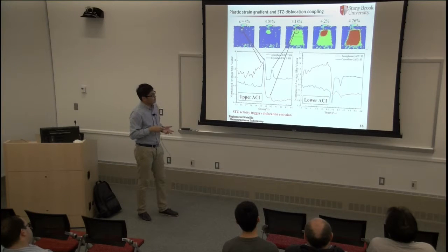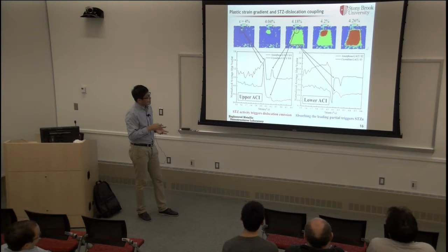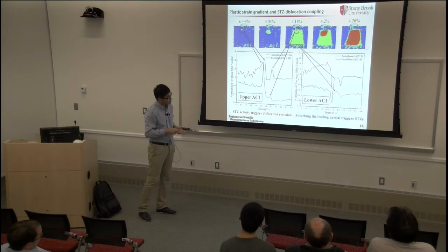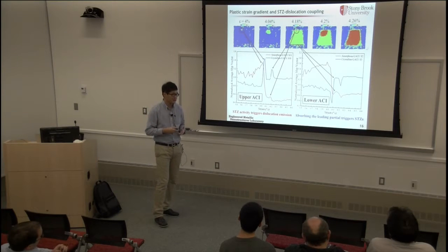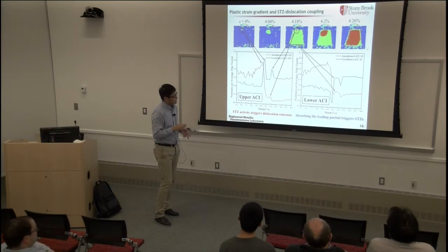And then when the dislocation propagates to the lower crystalline ACI slices, it corresponds to a surge of the crystalline LACI's S3 value, which later enhances the amorphous lower ACI's value. And this shows that absorption of the leading partial triggers the STZs in the lower amorphous layer.